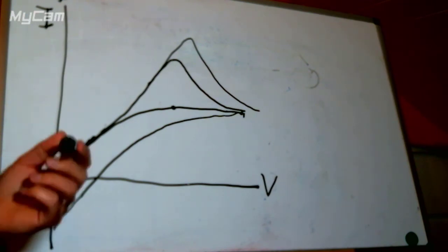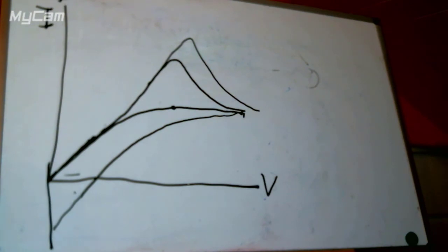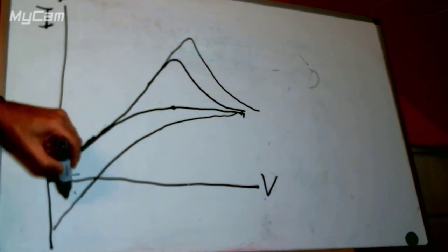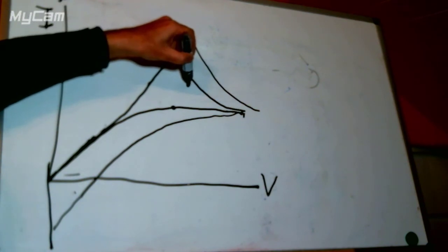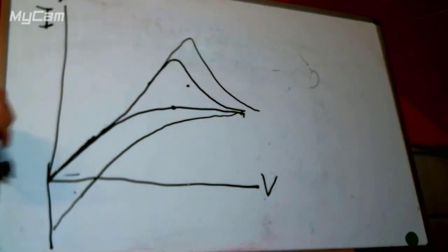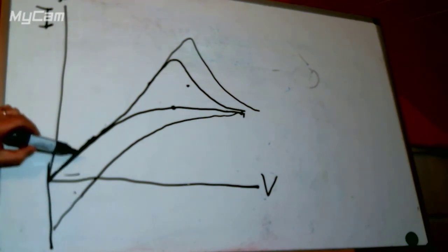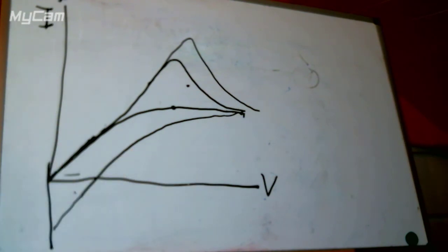If we carry on sweeping up and down, we will eventually get to a steady state, but there will be a gap between these two, which is how much copper we make up here and how much copper we use up at the bottom end. That will determine how much space there is between these two lines, which are effectively the upsweep and the downsweep. So that will do for today. We will come on to what happens with oxide layers next time maybe.